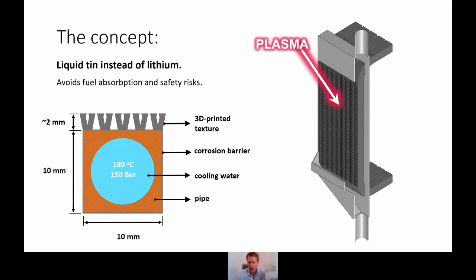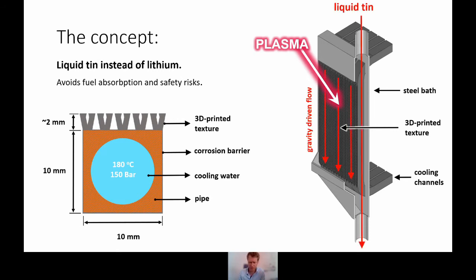Actually, we have to build a vertical wall. So it has to stand straight up. It has to be about a meter high, actually 70 centimeters. So that's why it has this orientation. This is the 3D printed texture. It sits on top of these cooling pipes that are curved towards the back, as you can see. And the whole thing is actually placed inside a bath. So the idea is to get a good cover over the whole surface, to get this reliable.